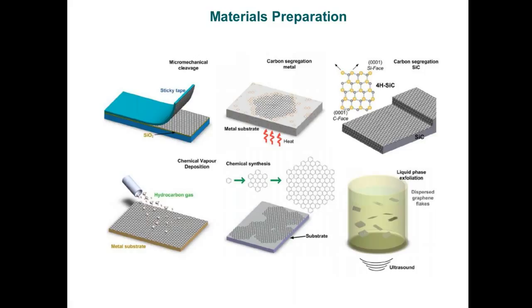What has been utilized mostly in laboratories to harvest graphene and graphene oxide in larger quantities is through exfoliation methods, which is basically taking graphite plates and using an oxidative process to disperse the graphene, and in the process you convert graphene to graphene oxide.